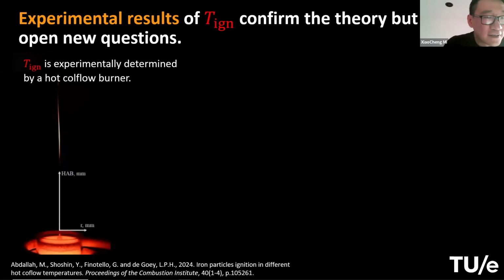Okay, I will continue. So this is a theoretical prediction. We need experimental verification. What I'm showing here on the left is an experiment also done in our group at TU Eindhoven. It's a single particle ignition experiment. Basically, you can inject single iron particles in this middle tube. It's a very thin ceramic tube. And around it, this larger tube carries a hot co-flow. You can use electric heating elements to heat up the co-flow gas that has oxygen in it, and you can control its temperature. In this way, you can determine the particle's ignition probability at different temperatures.